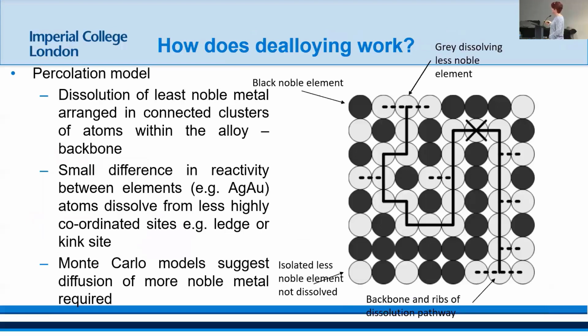So this percolation model basically says if I've got a less active element that wants to dissolve, in this case silver in a silver gold alloy, there has to be a pathway for the silver to get out. If there's not a path for the silver to get out, then it will passivate with pure gold across the surface and you'll just get a bulk surface. If you've got enough silver, they all connect and you can create these porous networks.